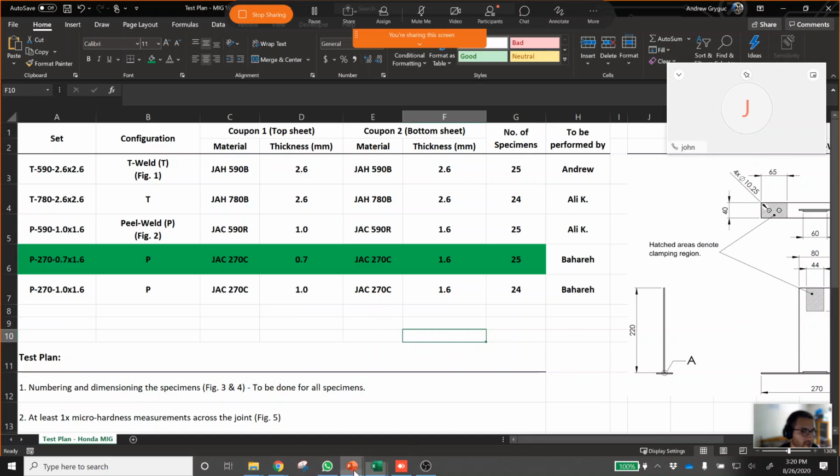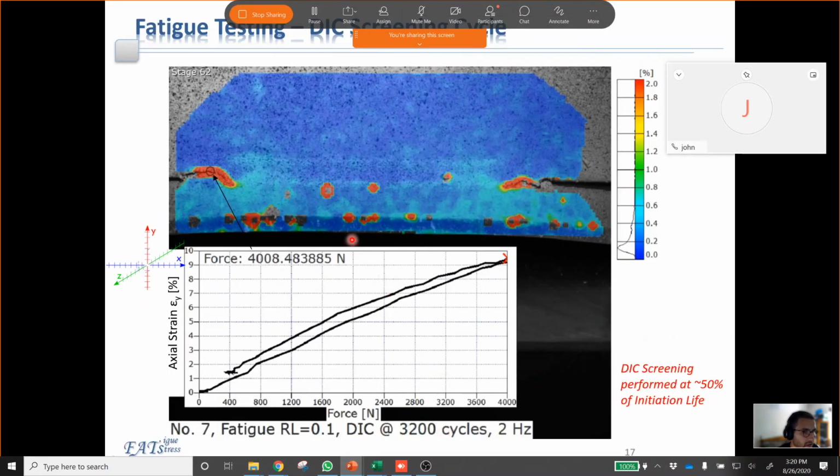So just a final slide here. We're performing DIC measurements on the full field strain on the entire image that you see here. And we can actually provide, in this case, the axial strain in the crack opening direction. This crack is a little longer than the threshold, but we've done this at specific intervals. I've just chosen this slide because it's more obvious what we're looking at, because the crack's slightly larger. But in general, what I'm thinking that you need is the strain in the region.